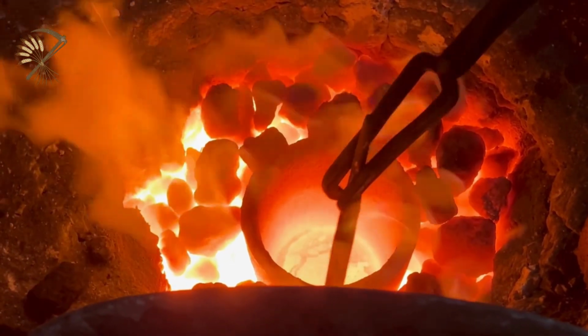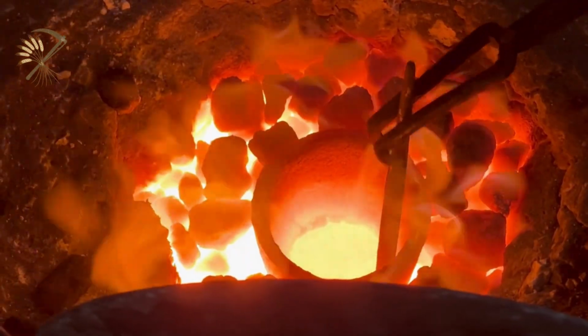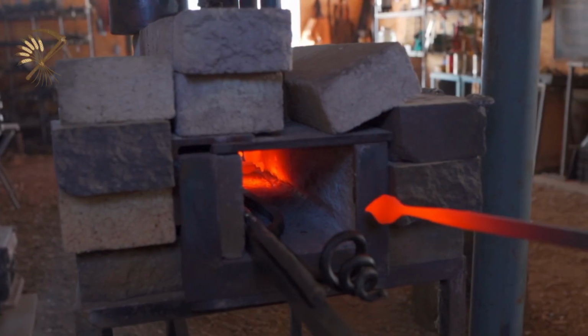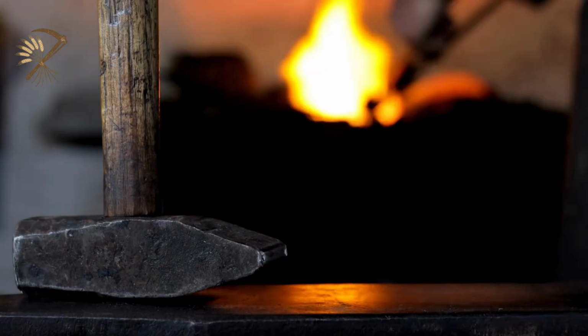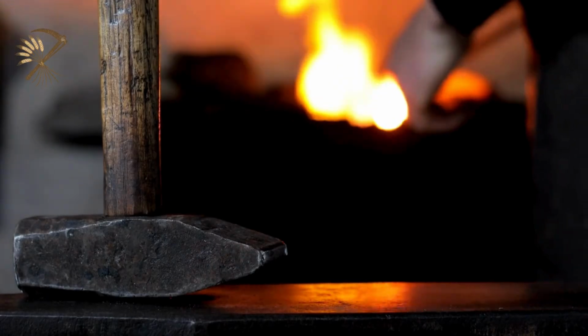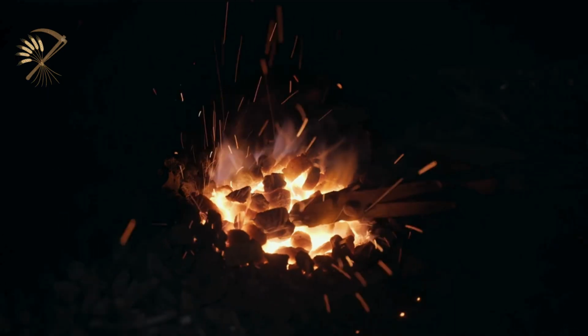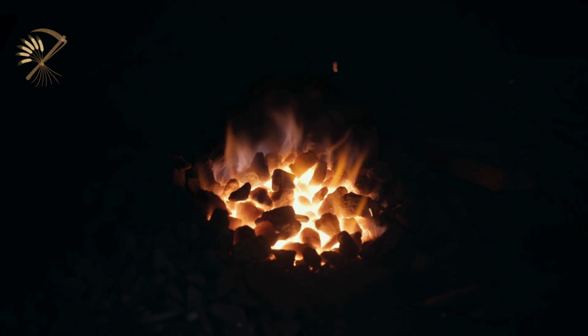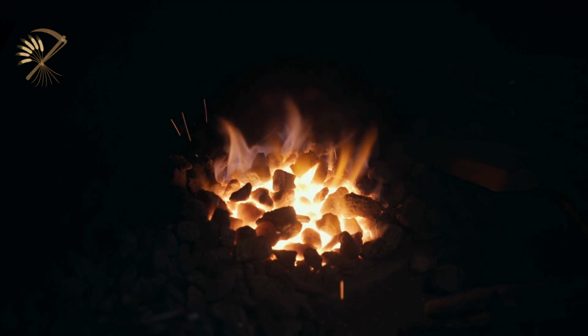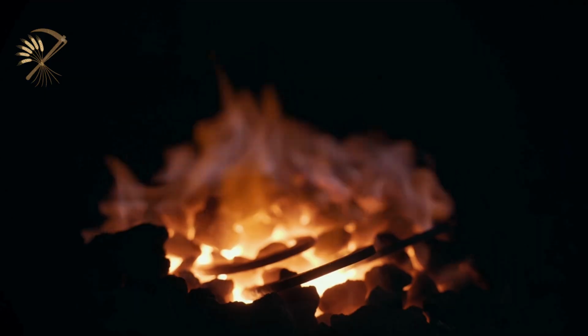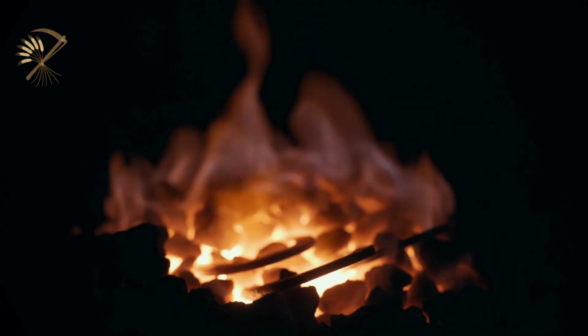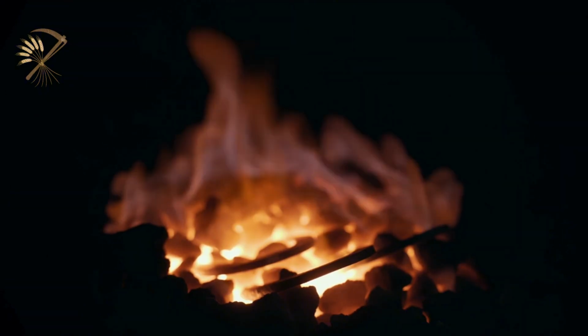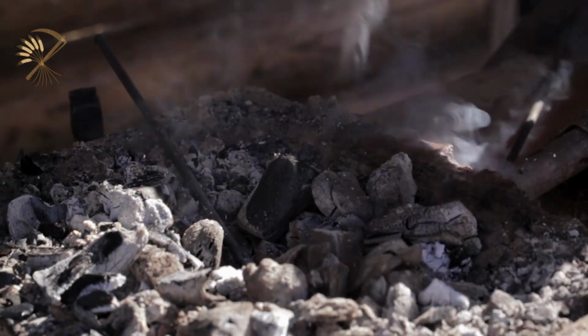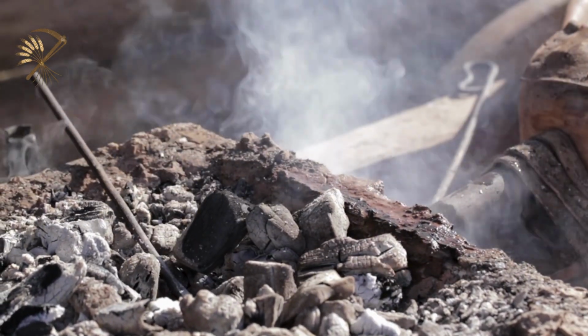The hardening begins by heating the shaped tool to 1450 to 1500 degrees Fahrenheit, the critical temperature where steel's crystal structure transforms from ferrite to austenite, allowing carbon atoms to move freely through the iron matrix. The smith judges this temperature by the steel's color, and by holding a magnet near the piece; steel loses its magnetic attraction at exactly the critical temperature, providing a non-contact thermometer requiring no instruments. The quenching plunges the heated tool into oil, typically vegetable oil or commercial quenching oil at room temperature. The rapid cooling locks the dissolved carbon in place, creating martensite, the hard, brittle crystal structure that gives high-carbon steel its cutting ability.